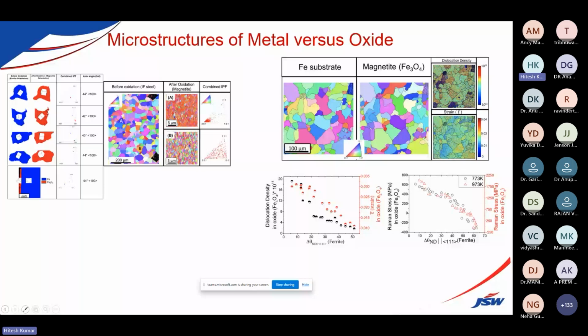So, okay, we thought, let's heat it above 570. The question is, why 570? You can ask. 570 is the temperature where the eutectoid transformation takes place, where Fe plus Fe3O4 is converted into FeO, wüstite. If you heat it above the eutectoid transformation and cool it down, a reverse eutectoid reaction will also take place.